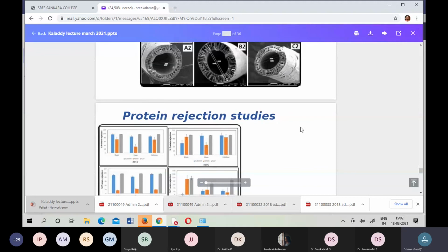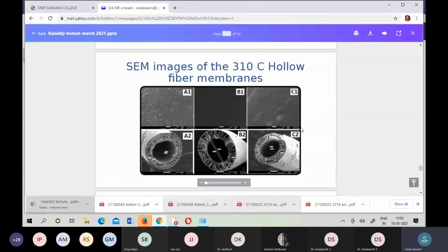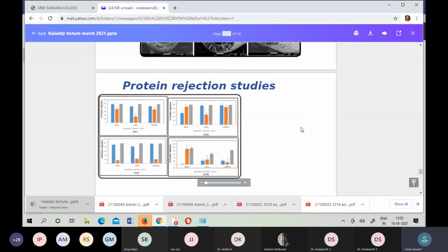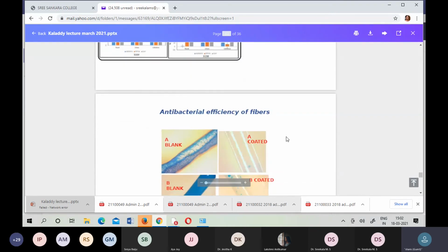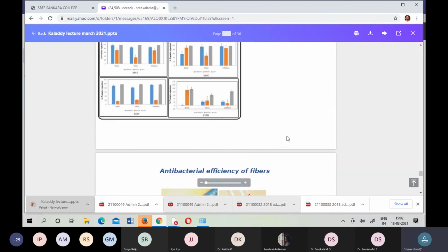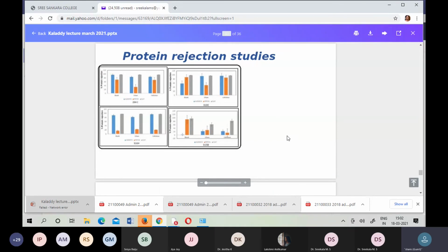So once we are sufficient, okay, we have a membrane. Instead of a normal PAN membrane, we have a chitosan coating. Even the chitosan coated membrane is showing good water permeability. That means the pores are not blocked. The pores are still open, because we use a very minimal concentration of chitosan. The chitosan layer is very thin. If you use a very high concentration of chitosan, you are blocking all the pores. In that case, it may not be a membrane. It's like a hollow tube, where you can only pass something inside the tube and have it come out.